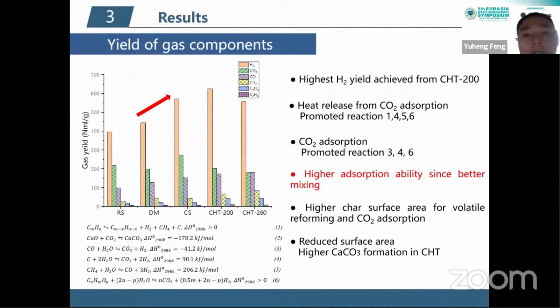And when we add calcium oxide in the wet condition, for the CS it has a higher hydrogen content. This is because of the higher adsorption ability due to better mixing. And after the hydrothermal treatment, the hydrogen yield is even increased, because of the higher char surface area.